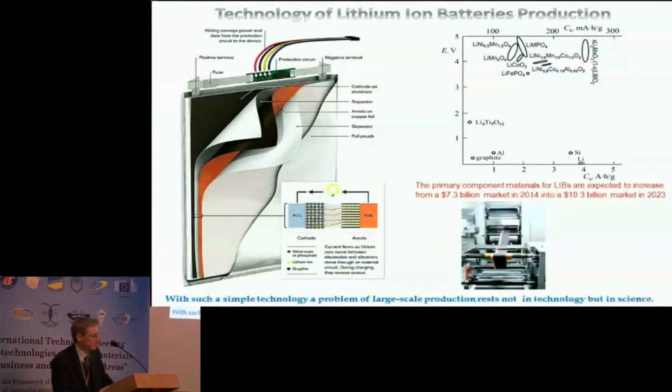Lithium-ion batteries consist of 2 electrodes in the form of thin layers on copper and aluminum foils, and a wet aprotic electrolyte separator between them. The main cell reactions in lithium-ion batteries are reversible lithium-ion incorporation and extraction in charge-discharge cycles between 2 insertion compounds. The positive electrode in current lithium-ion batteries typically consists of lithium 3D metal oxide or phosphate as active material. On the anode side, most lithium-ion battery cells use graphite-based active materials.